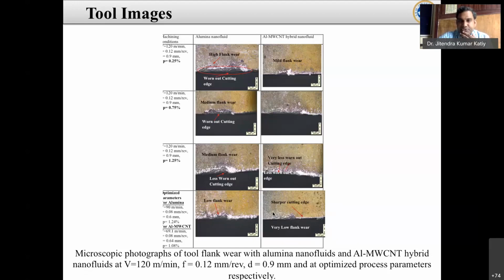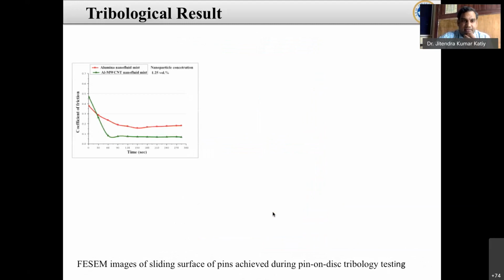So these are the tool images, and in this way we can calculate the flank wear from these tool images. Tribological results we can also obtain for both types of particles on the same pin-on-disk setup. Because here we use the alumina, there is nothing more that needs to be explained. Here you can see the alumina nanofluid's coefficient of friction is greater than that of the hybrid cutting fluid.